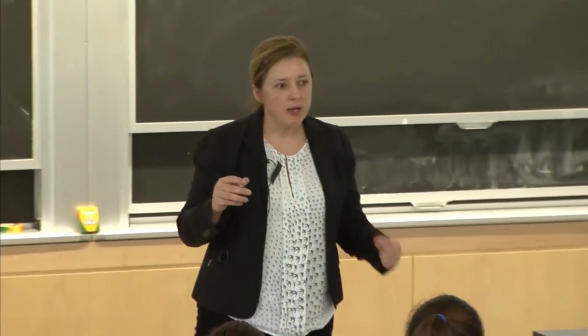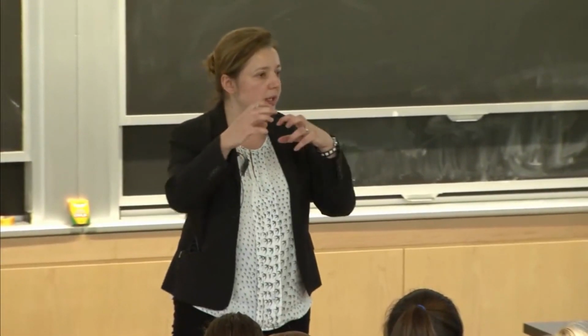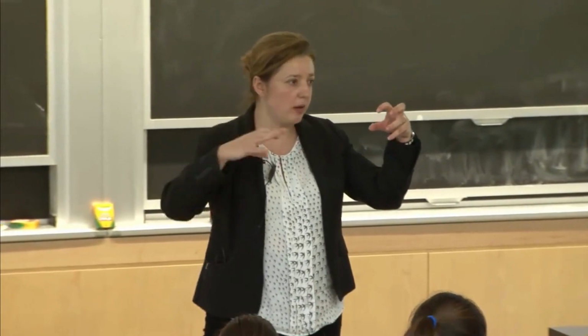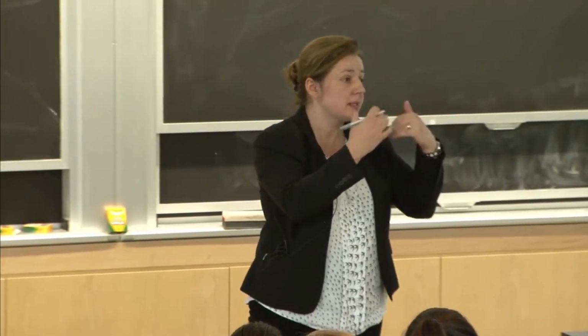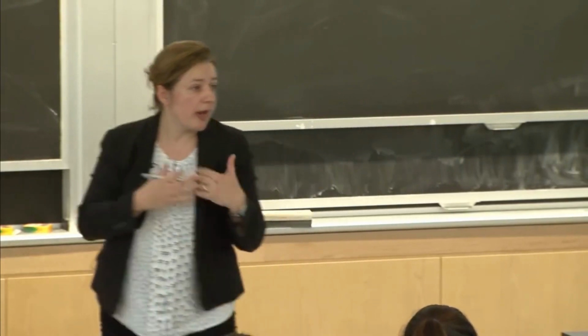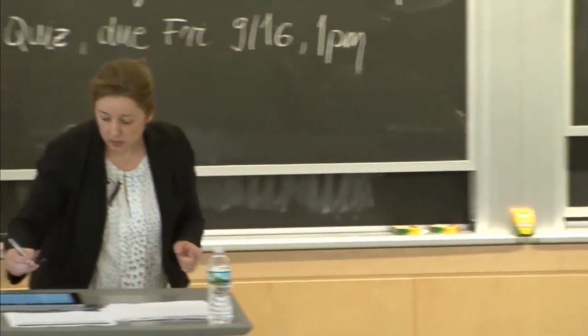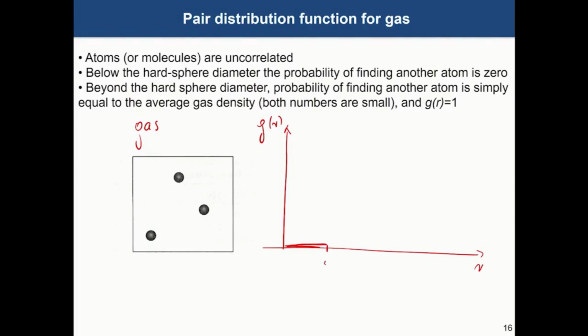In the gas, the atoms do not have any correlation, so they can be any place in the available volume, right? And the closest distance at which they can be is still 2R0, right? So for any material, the function will be 0 until we reach 2R0, right? So how this function will look, it will simply go to a value of 1, and it will stay there.